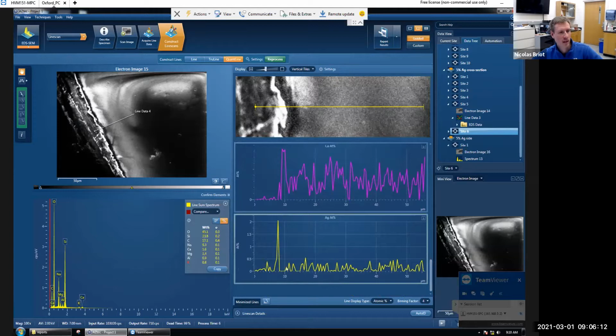Yeah, again, look at the percentage. It's just really noise. So our thought process was, okay, maybe when it's embedded and we grind and we polish, it had a tendency to damage the first few microns, or potentially more. So what we did is we put a similar sample. I think it was the same. Yeah, 5%.